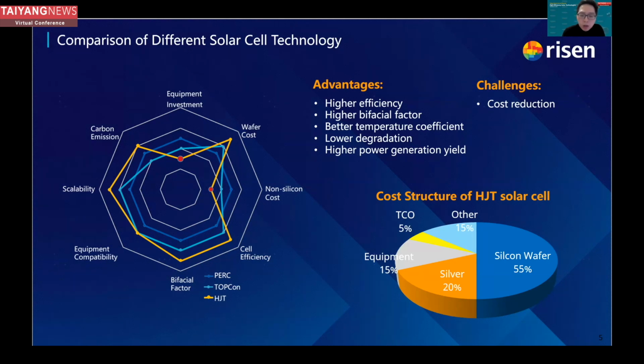Because you know that for heterojunction, we have to invest in brand new equipment. But I think this can be resolved when we reach whole industrial scaling up and ramping up. And for the non-silicon cost, we know that to have a better contact, we have to use low-temperature silver paste for the heterojunction and ITO as the TCO layer, which is costlier compared to PERC and TOPCon. So to